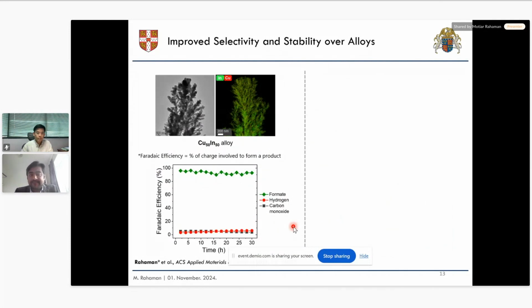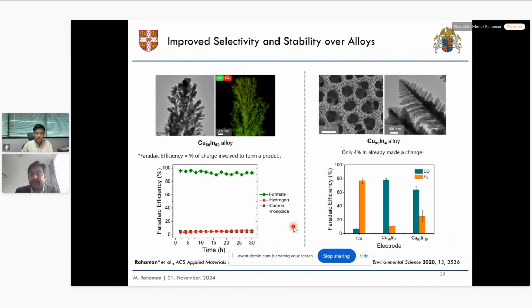So this is 50-50. How about a small amount, because indium is quite expensive? How about adding a small amount of this precious metal? Here we see around 4% indium. If we add that to copper, it already makes a huge change. For example, we made this dendrite. It's a macroporous structure, with only 4% indium in the copper moiety.